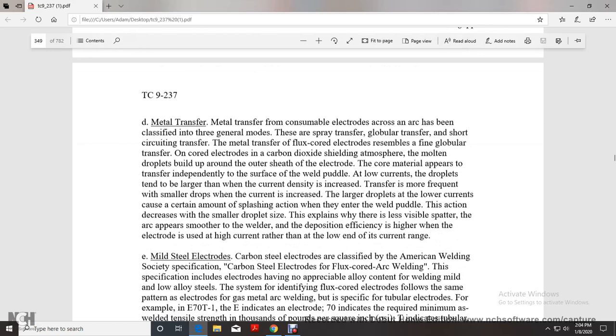Metal transfer. Metal transfer for consumable electrodes across the arc has been classified in three general modes: spray transfer, globular transfer, and short circuit transfer. The metal transfer for the flux cored electrode resembles a fine globular transfer. With the carbon dioxide shielding atmosphere, the molten metal droplets build up on the outer sheath of the electrode, and the core material appears to transfer independently to the surface of the weld pool. At low currents the droplets are larger. As the current density increases, the transfer becomes more frequent with smaller drops. The large droplets at lower current cause a certain amount of splashing action as they enter the weld pool.